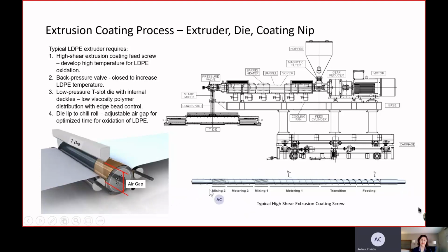So in order to do that, we use a screw, which this is a typical high shear extrusion coating screw. This has a short feed section, a transition, and then a long metering, mixing, an additional metering and mixing. This is all done so that we have the time and the shear energy to put into the polymer to raise this melt temperature and get a good condition for low density polyethylene to create the temperature for the oxidation to get the bond as we coat.